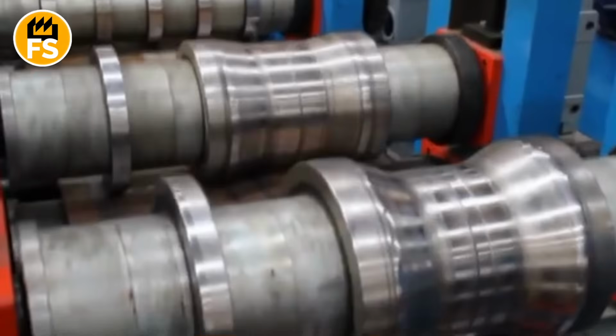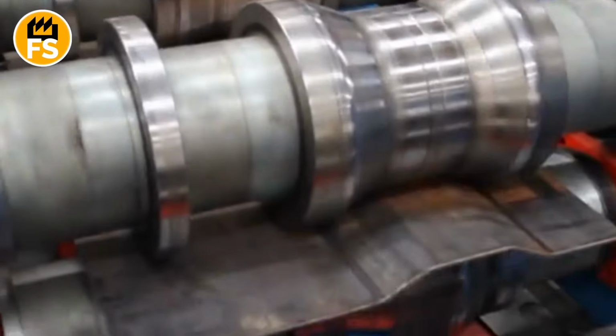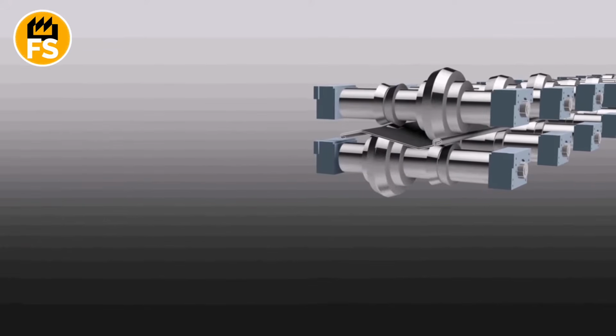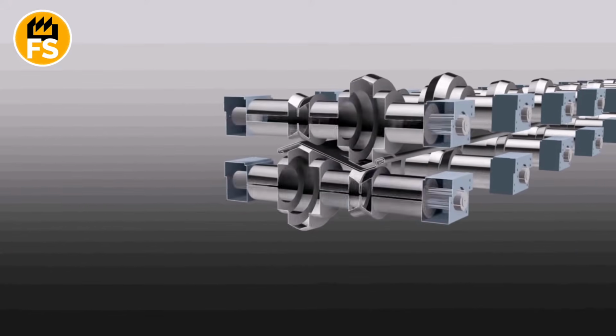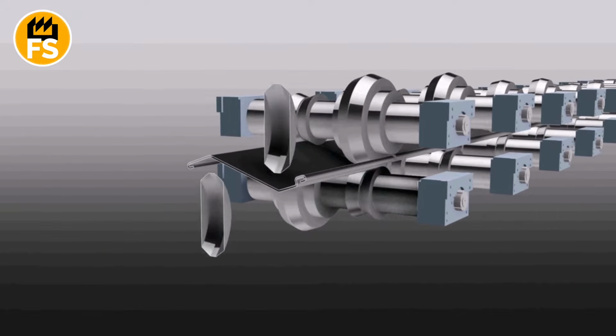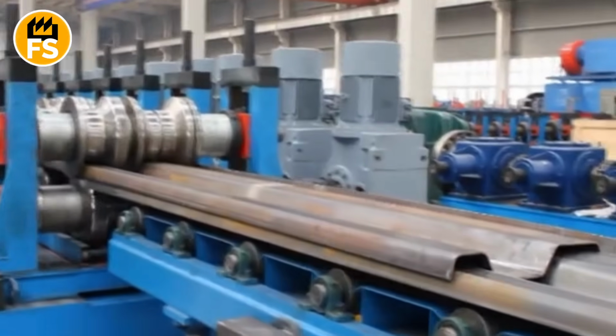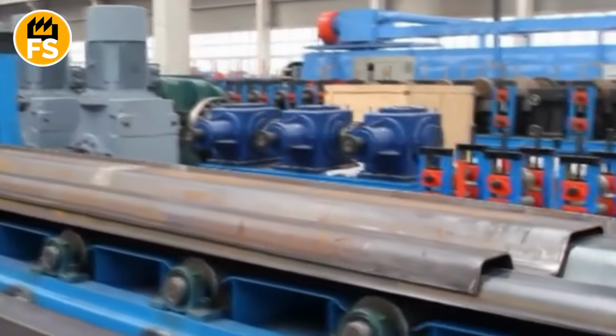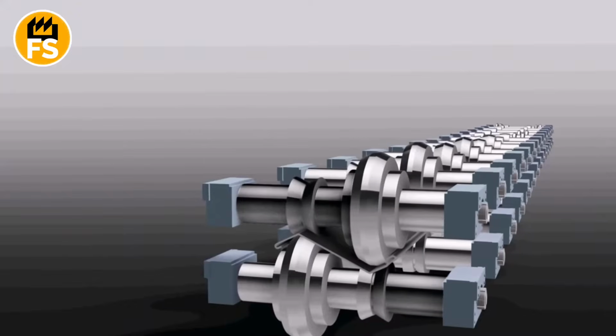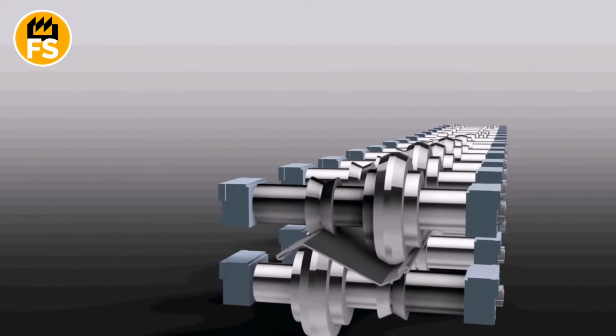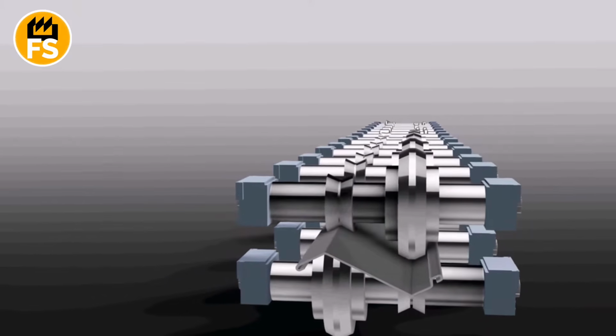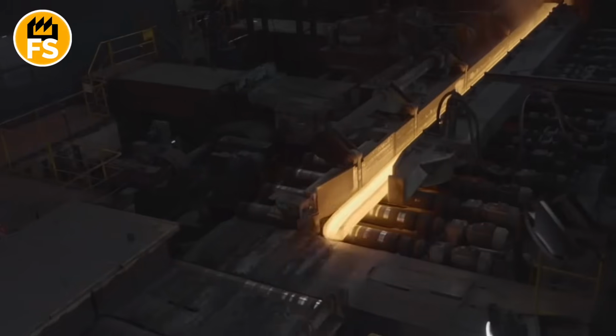The slab flies into the first pair of rolls with a roar, which squeezes it and begins to form the main profile, usually Z-shaped or U-shaped. Then it passes through the next pair, which further refines the shape. And so, step by step, passing through dozens of such rolls, our flat bar is transformed into a long, ribbed ribbon before our eyes. We talked about locks or interlocks. Well, the tolerance in their manufacture is only a few hundredths of an inch. That's less than the thickness of a fingernail.